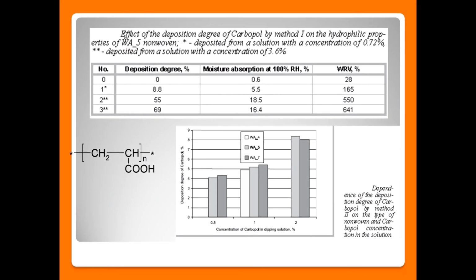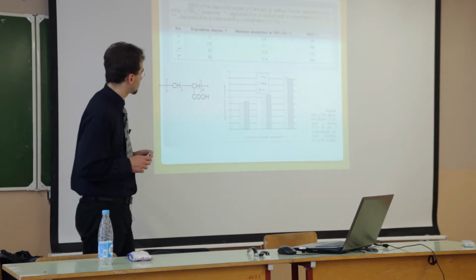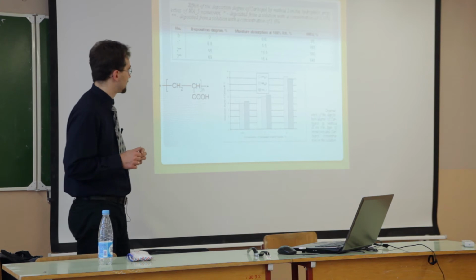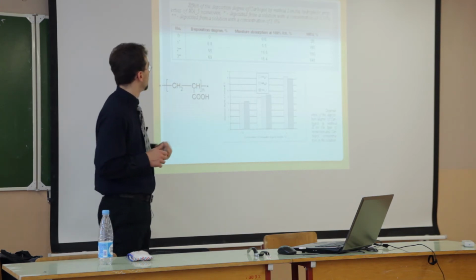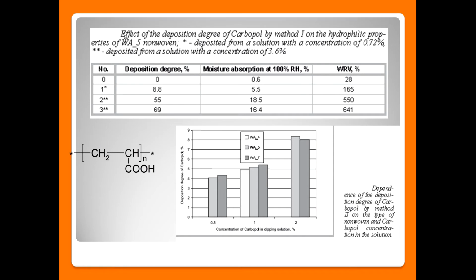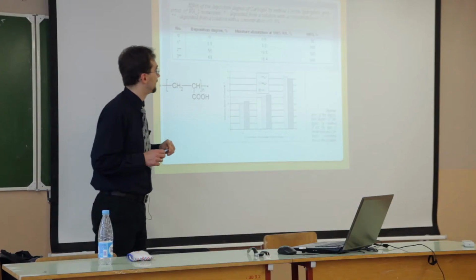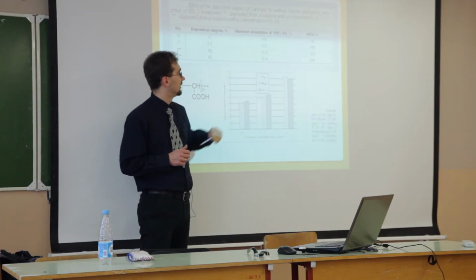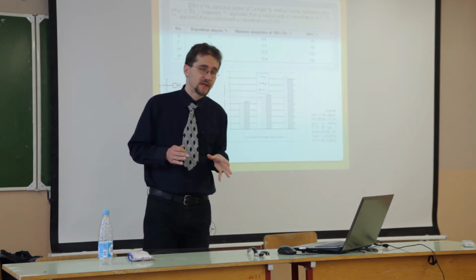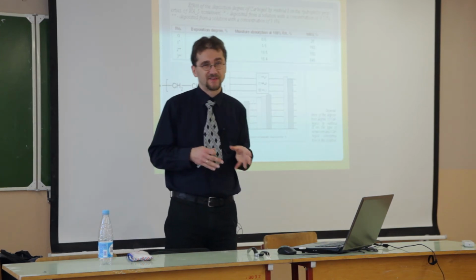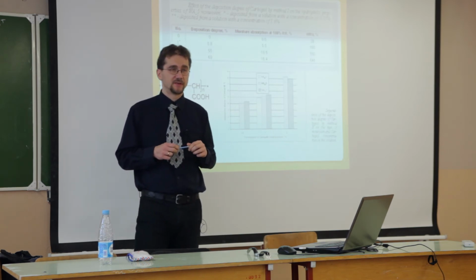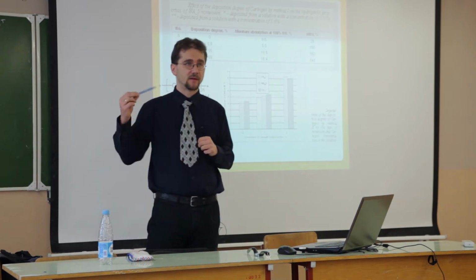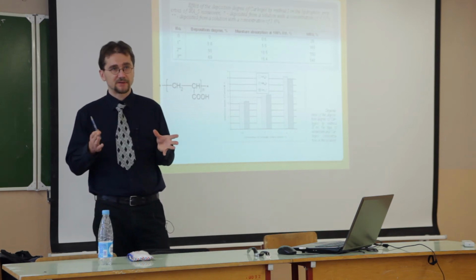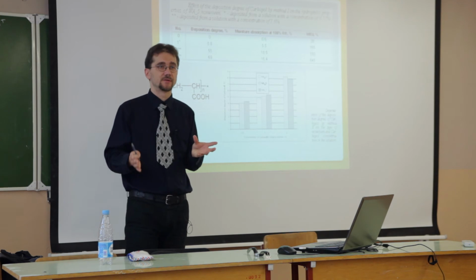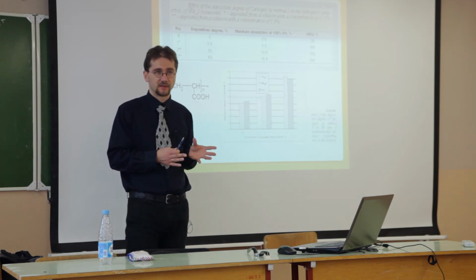Again, we used polyacrylic acid for padding, and we used different concentrations, and finally, using different concentrations of polyacrylic acid, we received different deposition degrees and different hydrophilic properties. So it can be also an efficient technique and very easy, but we have to remember that the connection between the external layer and the main material is very weak. It is not as strong as by grafting technique.